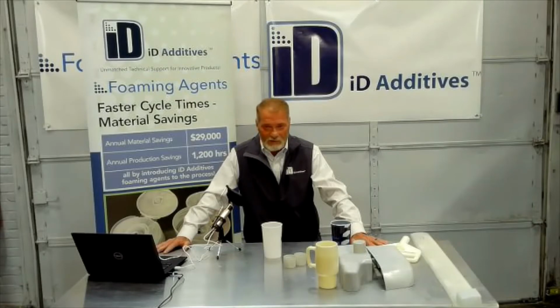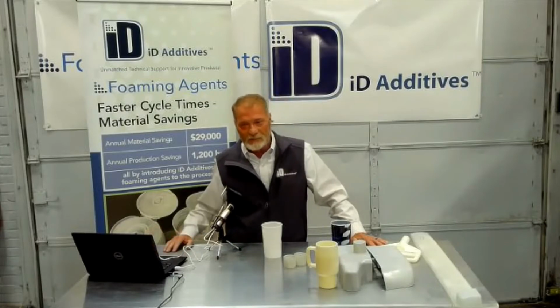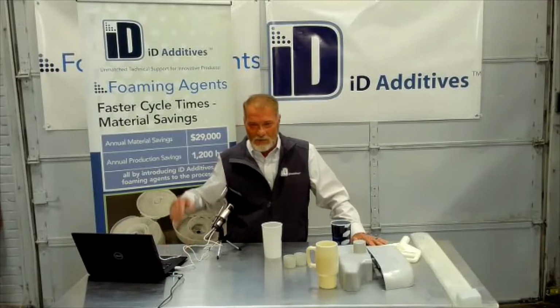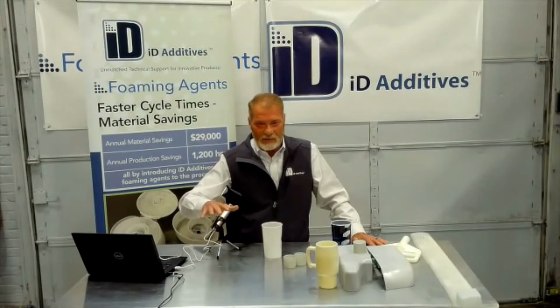Okay. Next question. Is there an additive or chemical material that we can use to reduce the temperature of additive decomposition? So you're talking about our materials? As far as decomposition, we have materials that kick off at 325. We have materials that kick off at 380. We got materials kicking off about 420. So we do have a range of products that kick off at different temperatures. I hope that's what you're asking. If it's not, please let me know.